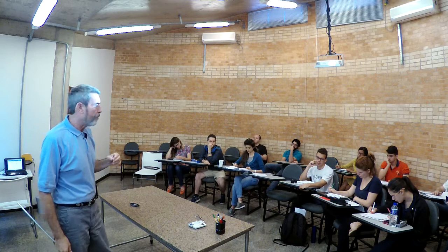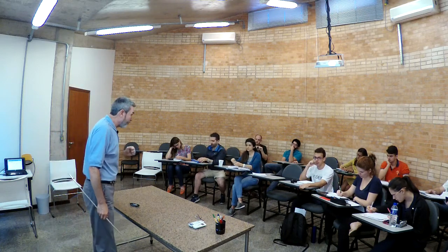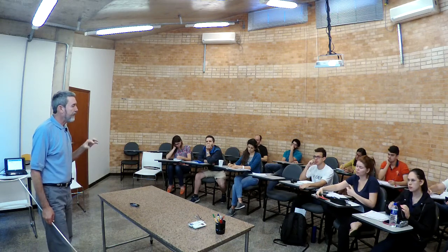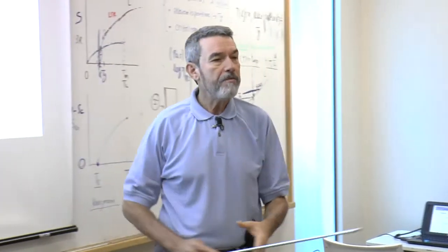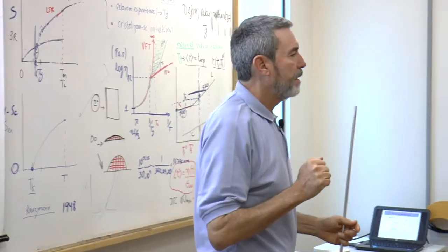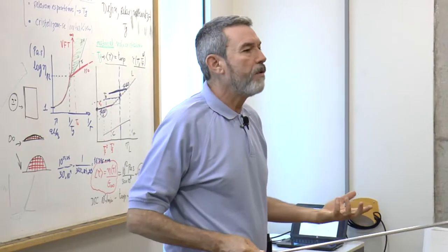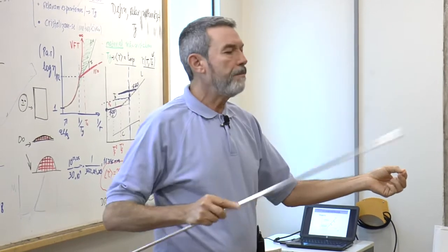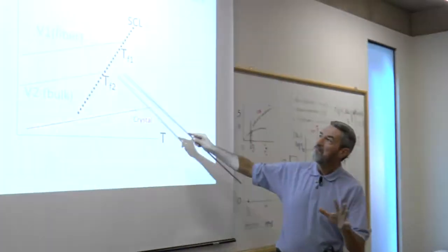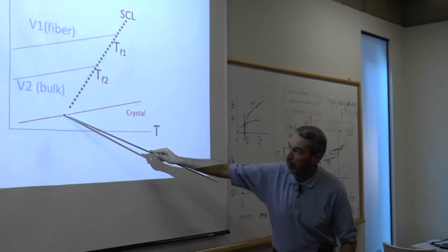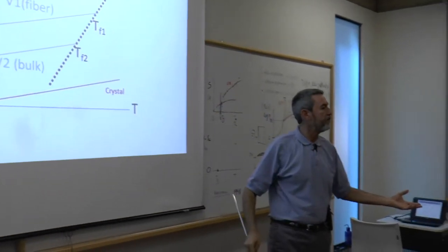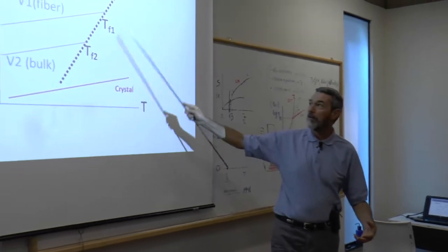I should say that there are ways to measure TF. And if any of you are interested, later on we can talk about this. But the idea I want to convey now for this class is that TF is where the glass was frozen. Tg depends on how we measure, depends on the heating rate, and depends if we do it on the heating path or on the cooling path. It's related. Tg is not here or here. It'll be somewhere here, but it can be 100 degrees off in practical terms of TF1 or TF2.